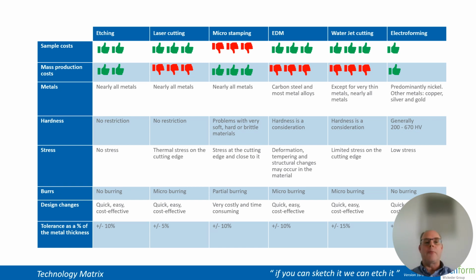On the other extreme, mass production, we see that laser cutting, water jet cutting, and EDM get very expensive. And microstamping is economically the preferred technology. But also etching is a very good alternative for mass production. And in the middle, you find a balance where etching is the most cost-effective technology. Some other comparison: etching, as I already told, gives a product without any stress and with no burring. This is something that is very hard to achieve with other technologies. And if we compare tolerances, we see that everything ranges approximately around this plus or minus 10% of the material thickness.